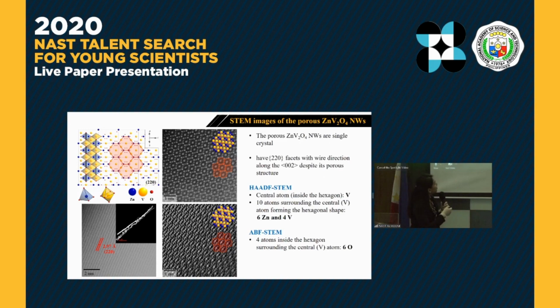This hexagonal pattern is composed of 10 atoms, 6 of which are zinc, and the 4 less prominent, less intense atoms are vanadium, while the central atom is also a vanadium atom. However, oxygen cannot easily be detected using the HAADF, and thus we use ABF to determine the exact location of the oxygen atoms. Based on our ABF, we have a total of 6 oxygen atoms surrounding the central vanadium atom.